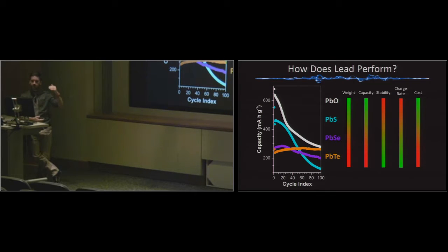So for instance, as you go down the periodic table, oxygen is the lightest material, and you want light materials for your battery, so that's green. As you go down, you get heavier and heavier, so that becomes red as you get to the worst side of the property. If you look at the capacity from this plot, you can see that you start out with lead oxide here at the top with the highest capacity. And that's because to calculate capacity, you divide by the weight of the material, so they're inversely proportional. And as you go down, you see it follows the trend of the periodic table, where the highest capacity is lead oxide, and then it's the worst with lead telluride.